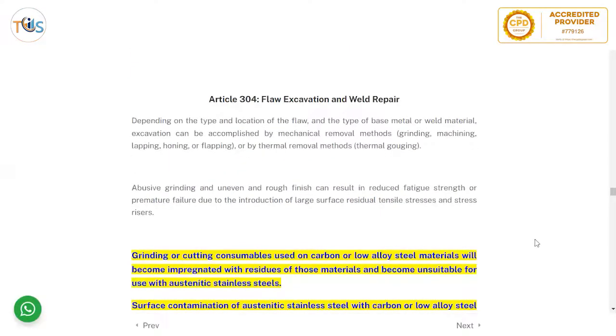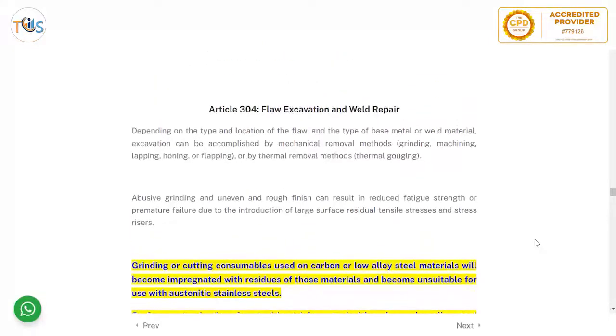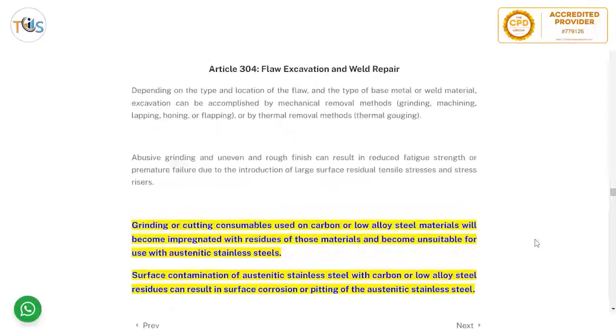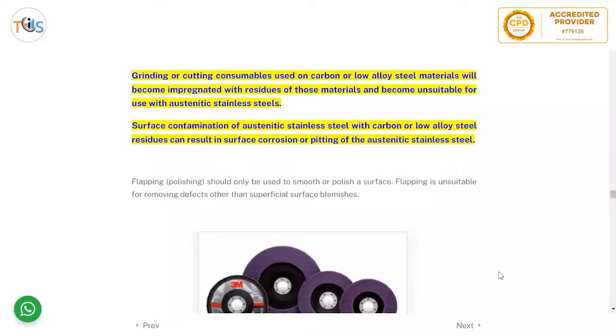Flaw excavation and weld repair: depending on the type and location of the flaw and the type of base metal or weld metal material, excavation can be accomplished by mechanical removal methods such as grinding, machining, lapping, honing, or flapping. Abusive grinding should be avoided because it reduces the fatigue strength, causing premature failure, by introducing large surface residual stress and stress risers. And grinding or cutting consumables used on carbon or low alloy steel material will become impregnated with residue of those materials and become unsuitable for use with austenitic stainless steel.